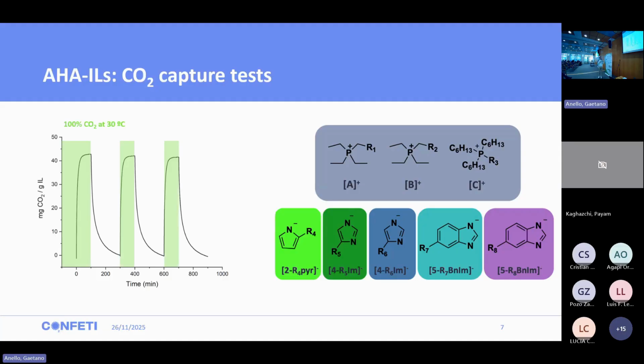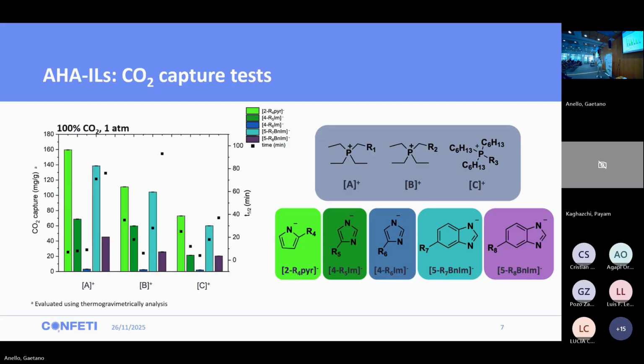So we apply a flux of CO2, or if we want to measure direct air capture conditions, simply dry air, at 30 degrees, and then for the desorption, we heat it up to 60 degrees in a nitrogen atmosphere. So the result is the capture capacity of the 5 ionic liquids up here in milligrams of CO2 per gram of material, and here you can observe the time to saturation of these materials.